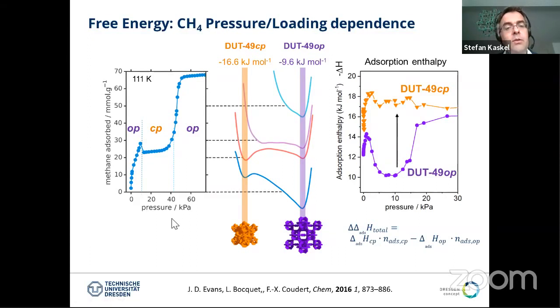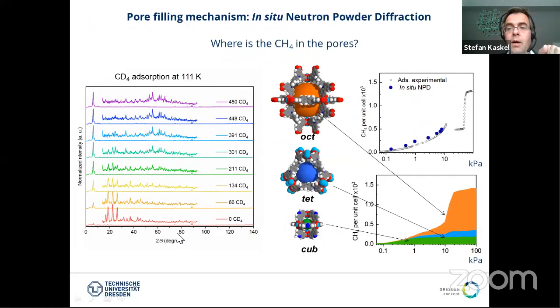Still, it is difficult to understand why there is this negative kink. And from the thermodynamic point of view, it's forbidden. That means that this state here is not a thermodynamically stable state. It's a metastable, long-lived state, similar to hysteresis behavior in MCM-41, basically, where there's also hysteresis between adsorption and desorption branch. So shortly before the mesopores start filling, we have a metastable state, and then we have a sudden contraction, and that basically pushes the gas out.